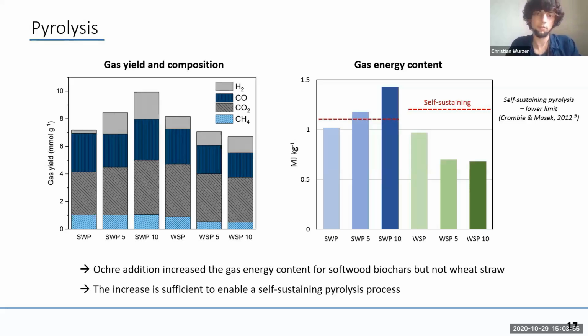And for the blue feedstock, so softwood, we can see that the increase in gas yield and hydrogen content significantly increased the gas energy content by about 40%. And most importantly, you produce excess heat if you use the gas on site. So you can use the excess heat for drying or other applications on the site, besides not needing any energy input for your pyrolysis reactor. The opposite was true for wheat straw, which was also expected due to the lower gas yield.